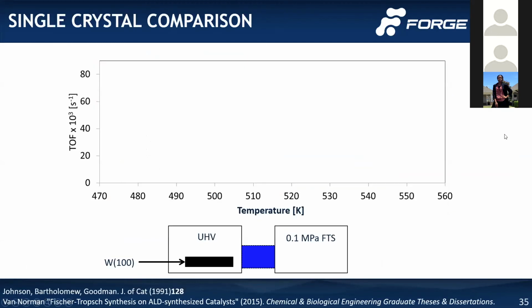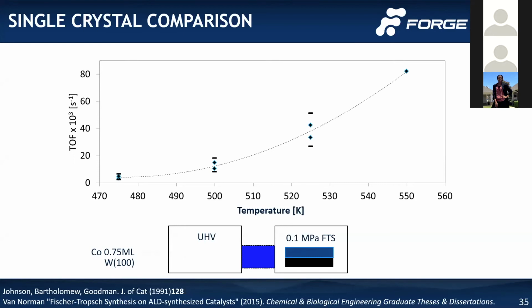So during my PhD, towards the end, we looked at other studies that looked at single crystal comparison. They took a tungsten single crystal in an ultra high vacuum chamber, deposited cobalt metallically onto that surface, then transferred it to a reaction chamber and looked at the turnover frequency with increasing temperature.